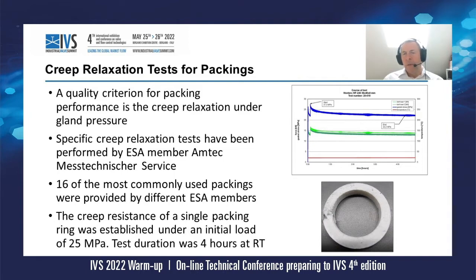In the graph here you can see one of the test results. The packing was submitted to 25 MPa, then there was a short holding time, and then it was retightened to 25 again, and the relaxation or gland pressure loss over 4 hours was measured. Also, after finishing the test and when the rings were extracted, the extrusion was checked.